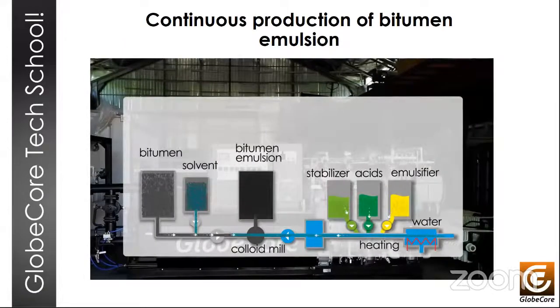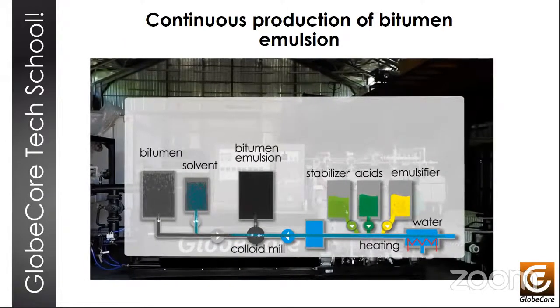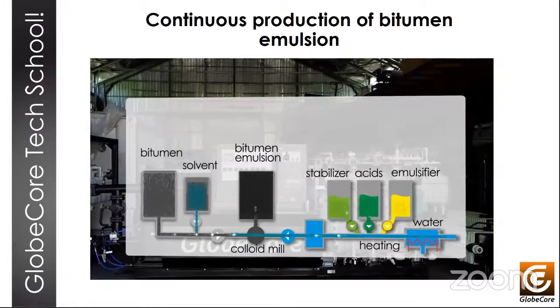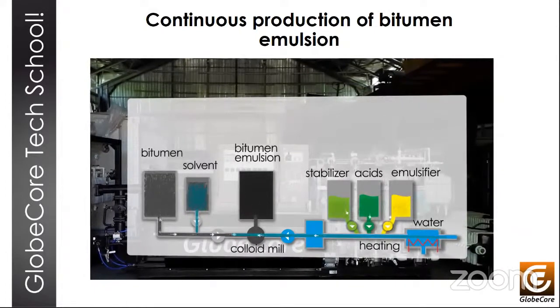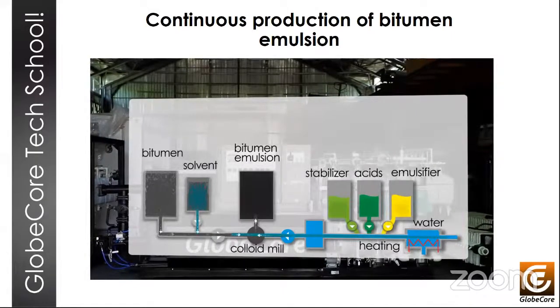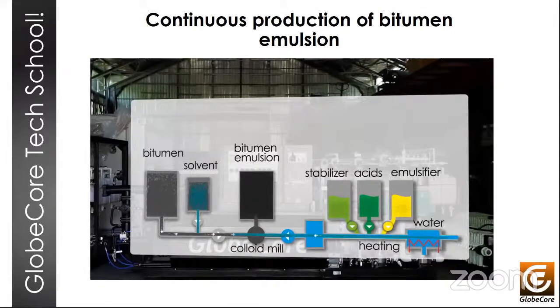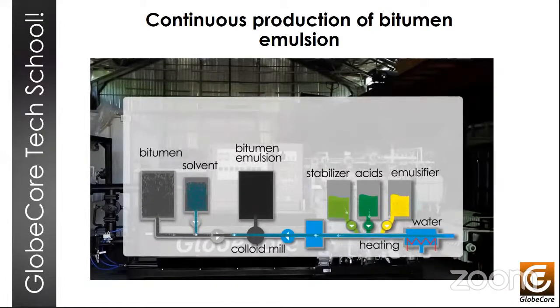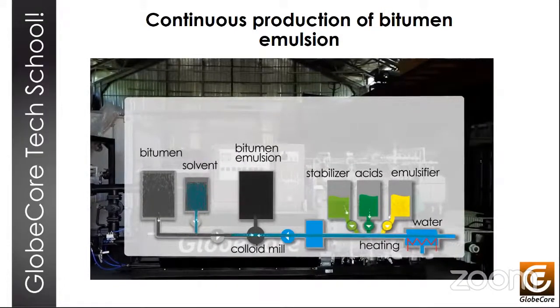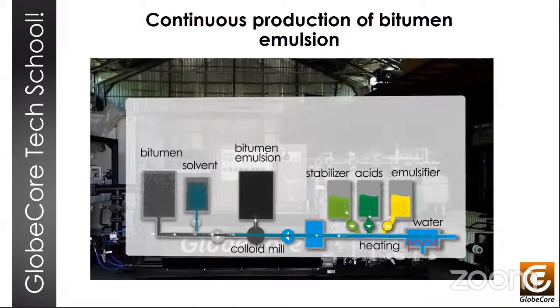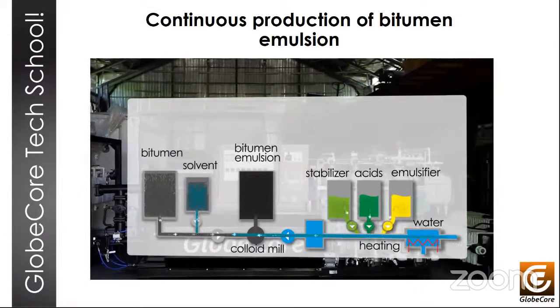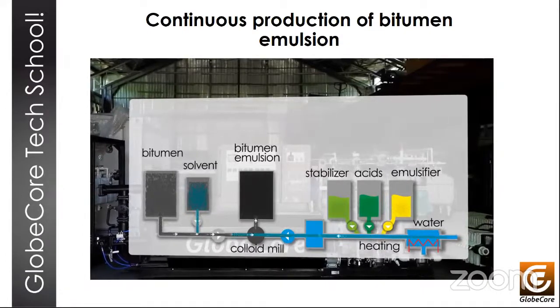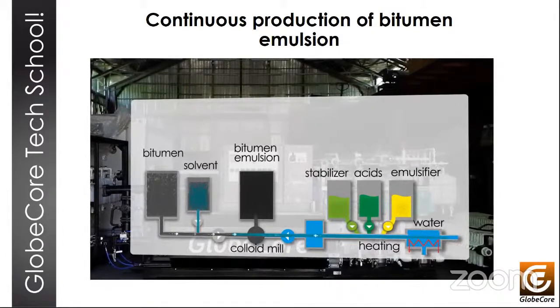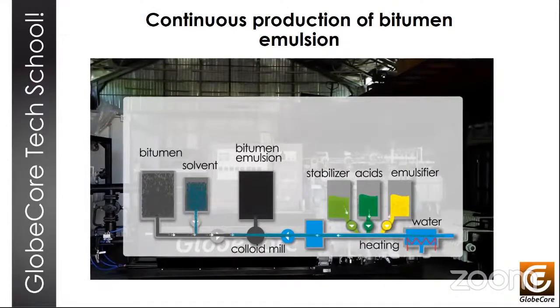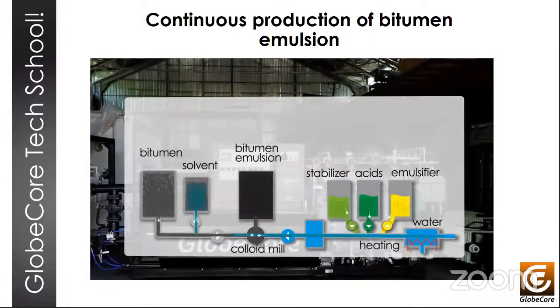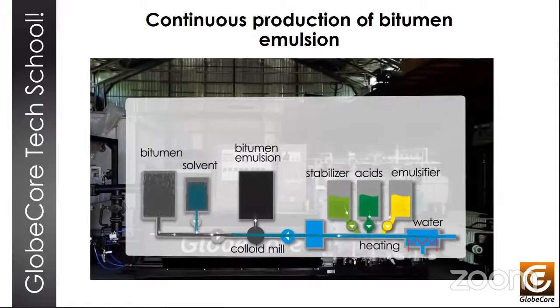In a continuous production process, water heating and dosing of all materials are performed continuously using separate portioning pumps for each material, and batch tanks are not used. Instead, the water phase supply system is designed to provide a sufficient time interval for the reaction between the chemical additives to neutralize and dissolve until the water phase combines with bitumen. This process requires the use of automated controls with flow meters for the dosage of all materials, with the exception of acid, the supply of which is controlled based on the measured pH of the water phase.